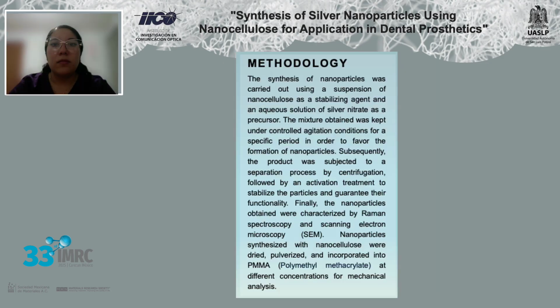life of patients. The synthesis of nanoparticles was carried out using a green method with the purpose of minimizing the use of toxic reagents. Nanocellulose suspension was used as a stabilizing and partially reducing agent, and an aqueous solution of silver nitrate was prepared as a precursor. Both solutions were mixed under controlled conditions of temperature and time, favoring the formation of the nanoparticles. This product was subjected to centrifugation because we need to separate the nanoparticles and eliminate impurities. Finally, an activation treatment, we can talk about this because we have a patent pending, was applied to guarantee the stability and functionality of the nanoparticles.